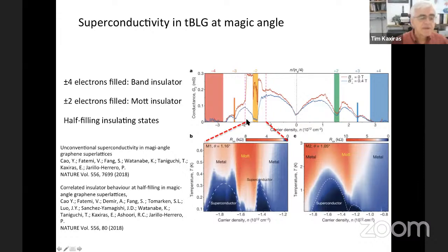And if you blow up just this region, and this is again the horizontal axis, the same axis, the doping, the carrier density, but the vertical axis now is temperature, and this is a phase diagram. For this temperature range, you see a superconductor and another superconductor here. This is a Mott insulator. Here you see a metal, and so on. The superconducting behavior was a surprise, and the mini gaps also were a big surprise. And these cannot be accounted for by the single particle picture.